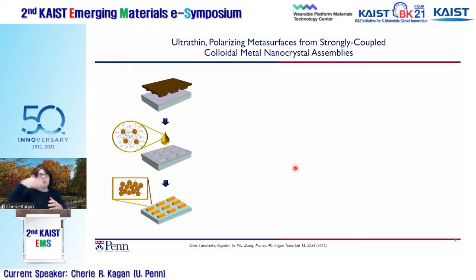Going a little further, and I'll jump a little faster in time, we were using imprint lithography. We could make more complex structures. We started working on rod-based structures. We could use these inks or dispersions of nanoparticles and spin coat them over large areas as well. In this case, we're using a resist to do the imprint instead of directly imprinting. Both processes work. And then we could do the ligand exchange and convert these into metal structures.